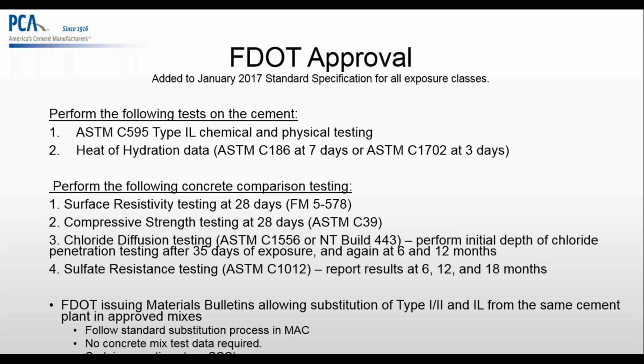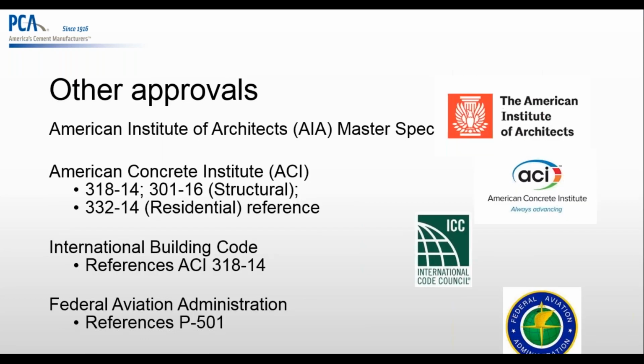Once that is done, then the FDOT issues a material bulletin where it will say that they are allowing a substitution of type I/II by the type IL, right? So there is a battery. There's a lot of testing that has to be done in order for the FDOT to approve the PLCs in their projects, meaning that all of the test results have to be successfully achieved before anything can happen, right?